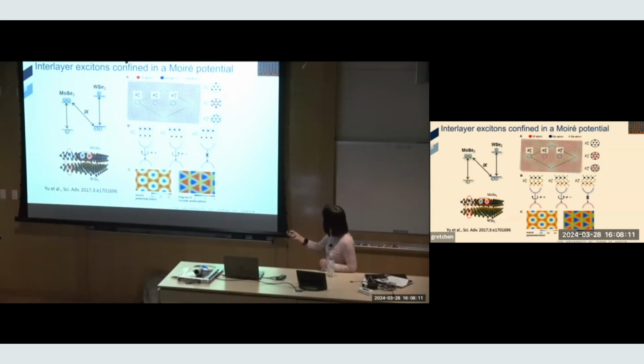It turns out if I can manage to create an electron hole pair at one of these 3 locations, they follow different selection rules. So now I have a material, not only do I have energy modulation periodically with a period anywhere between a few nanometer to a micron, which you can control with a twist angle. The energy modulation can be on the order of 200 meV, shown by the STM measurement. There's also a polarization pattern for light emissions. If I were to create the exciton localized at these locations, I would actually have this polarization emission pattern for one valley, and the opposite valley will reverse the selection rules.